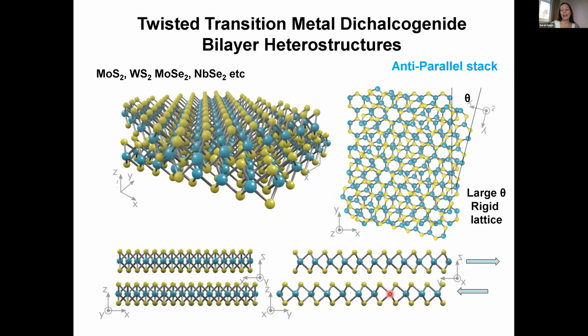If we look now at an anti-parallel stack, that's where we take the top transition metal chalcogenide layer and twist it by 180 degrees, and then apply a very small misorientation. So the lattice misorientation between the two layers will be 181 or 179. You can see we then get different types of stacking, and we can classify this into regions that are this 2H type stacking, which is the standard stacking you'd expect in a perfectly aligned transition metal dichalcogenide. We also get regions of metal-metal stacking and chalcogen-chalcogen stacking, which again we'd expect to be unfavorable.